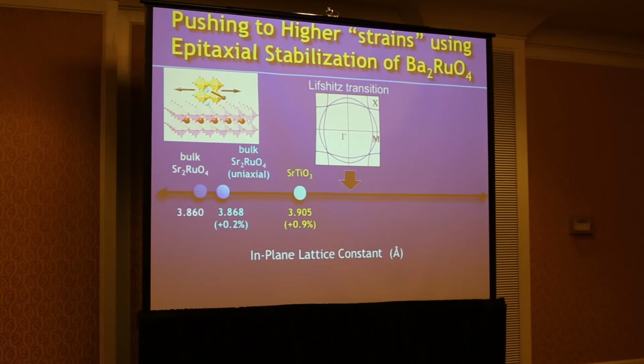And you can imagine, with more strain, we might get close to the Lifshitz transition, as what was an electron pocket around the gamma point turns into a hole pocket around the X point. But we need more strain to do that. And the way that we've done that is we've used a combination of substrates and chemical strain. So we switched from strontium ruthenate to barium ruthenate.